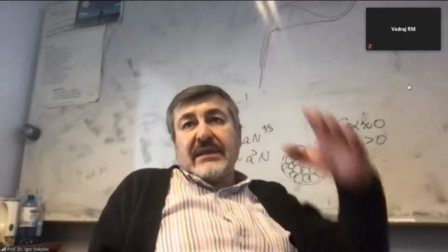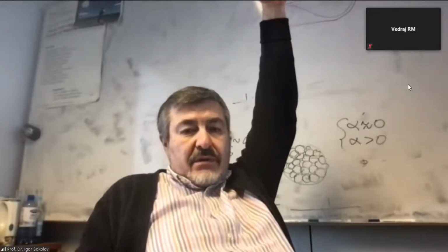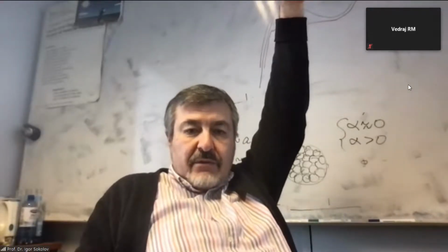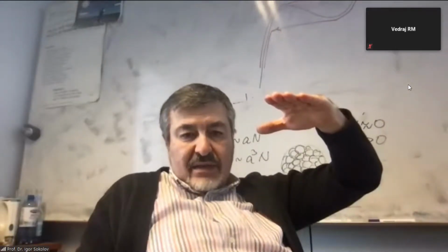and there interesting things take place. By crossing the theta line, above in the domain of a good solvent, you have swollen chains, you have self-avoiding walk chains. Close to the theta line, the chains are ideal.